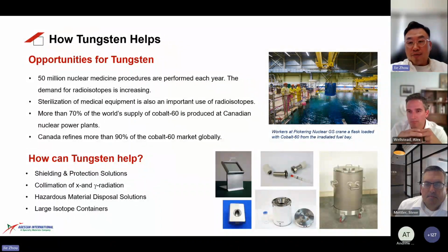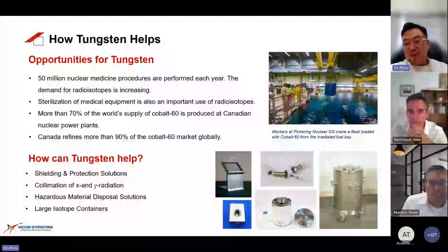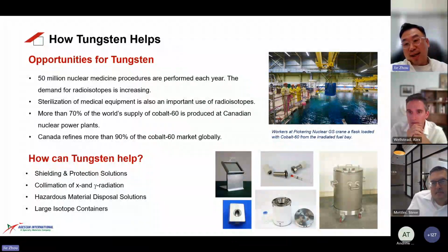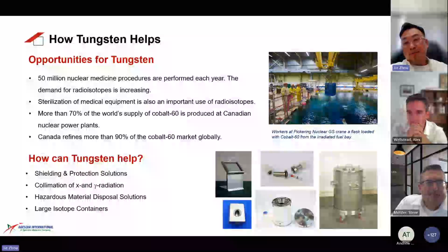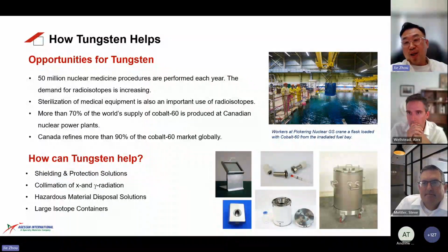Tungsten can offer a superior protection level to lead at an equivalent thickness. Like Mirion, they have a well-known product called ProTech PET shielding. With only 0.34 inch thick tungsten, it can attenuate FDG F-18 by 88%.